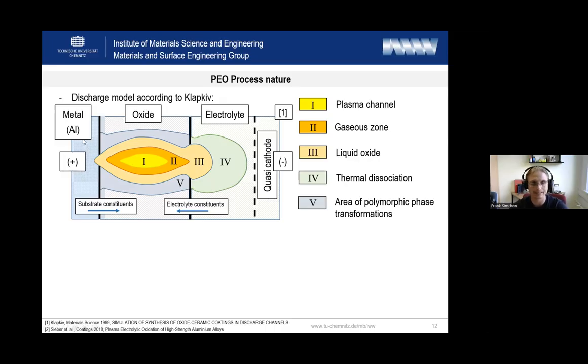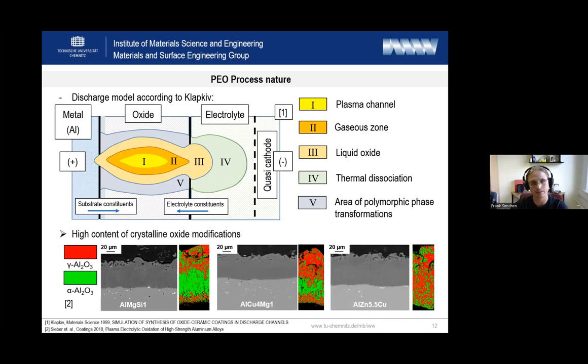We apply an alternating electrochemical pulse. So these discharges appear and collapse, and appear and collapse. And in this area of polymorphic transformation, there takes place a transformation of amorphous aluminum oxide into crystalline aluminum oxide. So the electrochemically formed reaction layer from the passivating step consists of amorphous aluminum oxide. And step by step these discharges appear and transform this amorphous oxide into crystalline oxide.